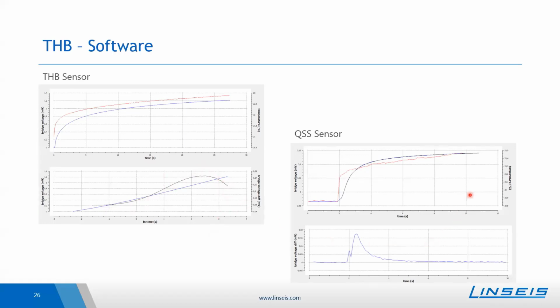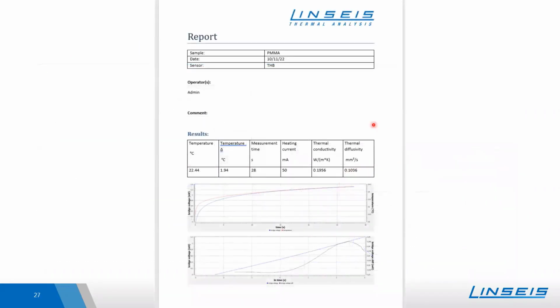For the QSS sensor, as it is a quasi-steady-state sensor, we need more or less a saturation, and this can be seen here in the bridge voltage. We see an increase, and then afterwards, more or less a stabilization. This can also be seen very well here, where the derivative goes back to zero, or more or less to zero, after it reaches a steady state. After the measurements, one is also able to export a report with the measurement data and also with the measurement curve. This will look similar to this one. One can export it as a Word document or also as a text document.